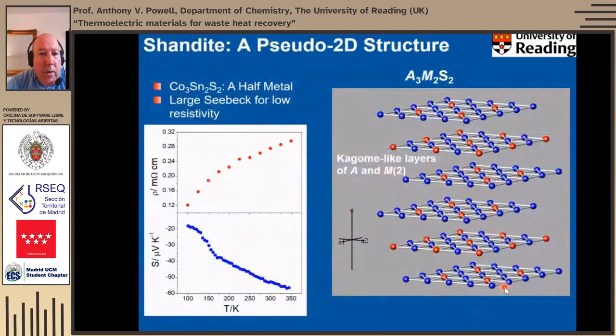So our first foray into sulfide thermoelectrics was what are called shandite, based on the shandite mineral. It's a half metal. It's unusual that it has a very large Seebeck for such a low resistivity. So at 350 Kelvin, its Seebeck approaches minus 60 microvolts per Kelvin, and yet the resistivity is still less than 0.3 milliohm centimeters. So it's quite an unusual combination.